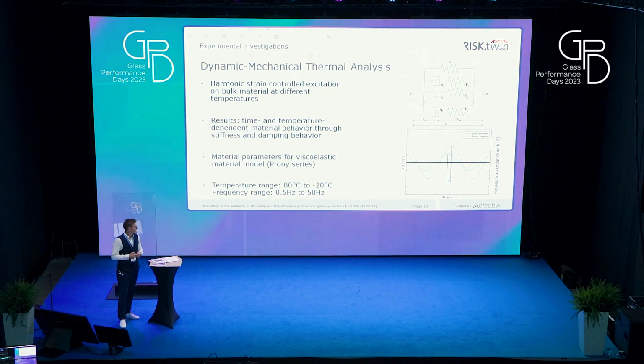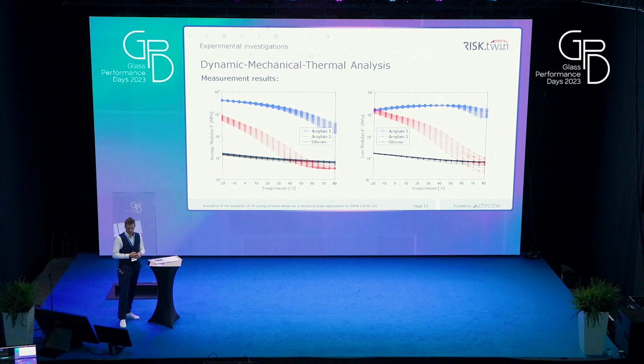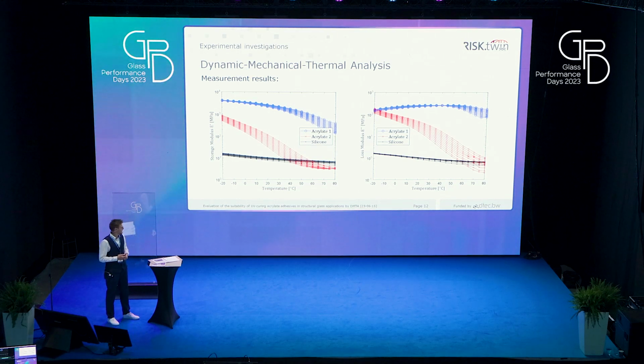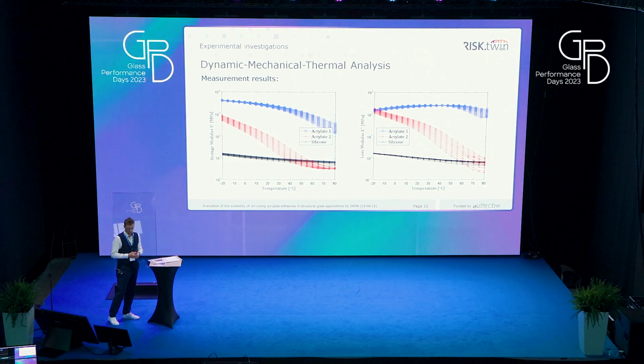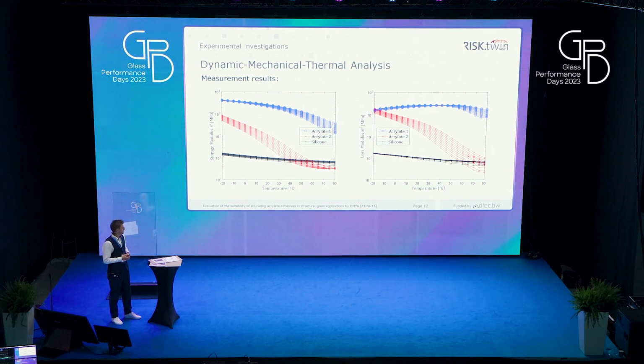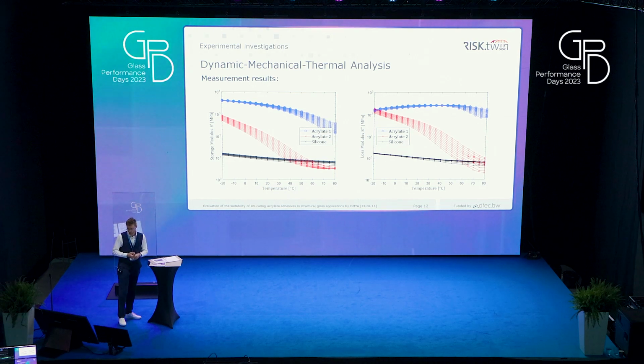Now, how do these measurement results actually look? You can see here the storage modulus and the loss modulus plotted over the temperature, and as I said, going from minus 20 degrees Celsius to 80 degrees Celsius. And as we can see, both acrylate adhesives exhibit much higher values for lower temperatures, but the silicone shows a much more constant behavior over the whole temperature range. And for higher temperatures, it even outperforms the acrylate 2.